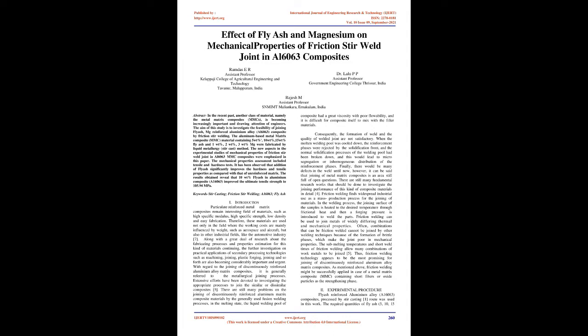With regard to the joining of discontinuously reinforced aluminium alloy matrix composites, it is generally referred to the metallurgical joining processes. Extensive efforts have been devoted to investigating the appropriate processes to join the similar or dissimilar composites. There are still many problems on the joining of discontinuously reinforced aluminum matrix composite materials by the generally used fusion welding processes. In the melting state, the liquid welding pool of composite had a great viscosity with poor flowability, and it is difficult for composite itself to mix with the filler materials. Consequently, the formation of weld and the quality of welded joint are not satisfactory.